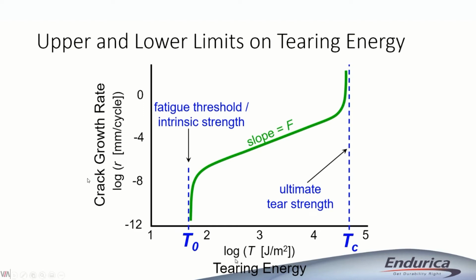Now, usually when you're driving a crack at some rate, you get a tearing energy. That tearing energy is the sum of T naught plus an additional component of energy that comes from energy that's consumed in the crack tip process zone. But if you get rid of the process zone, what's left is just the intrinsic strength of the material, and that's really the same as the fatigue limit. Now, between these limits, you end up with a characteristic slope. I've called that F here, and that tells you the sensitivity of the crack growth rate to the tearing energy.